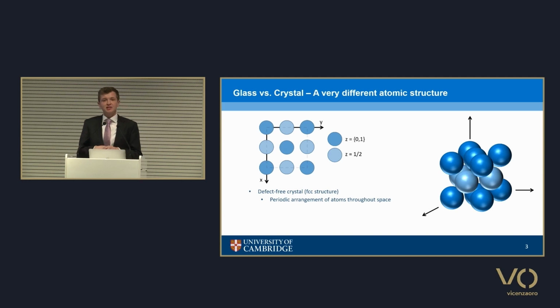So while it's tempting to draw comparisons between metallic glasses and polymers and oxide glasses, such as window glass and silica, we need to be careful because in those structures we have chains of atoms which are entangled together, which is not the case in metallic glasses. It's the atoms that are randomly distributed.